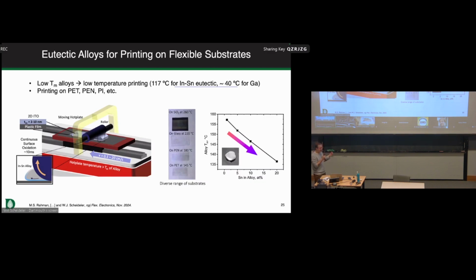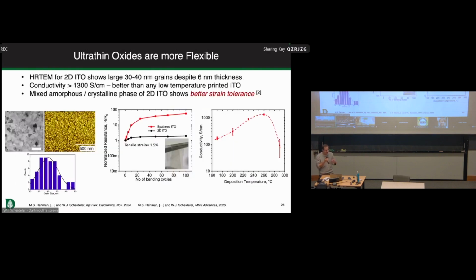One of the other interesting aspects of that kinetic control is that we can start to use materials that we can also print at lower temperatures. So one of the eutectics that we've been working on is a mixture of indium and tin. And indium and tin, if you're familiar with it from low temperature solders, melts at about 117 or 120 C. So you can bring the temperature down even lower. You can put it on a range of different plastic substrates. The surprising thing, though, is that even with this low temperature printing, we can get morphologies that can be highly crystalline, that can have relatively large grains.